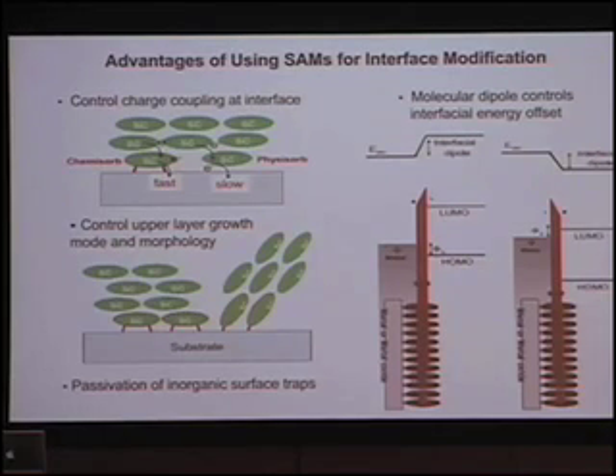Okay, and also you can utilize the SAM to passivate a lot of those hydroxyl-containing, or acidic hydroxyl group containing, surface traps. All those traps potentially decrease the efficiency of your devices. And the last one is to utilize the molecular dipole. Depending on the dipole's pointing direction, you can selectively either increase your work function, for example in this case to facilitate charge injection, or you can lower the work function, under your LUMO.